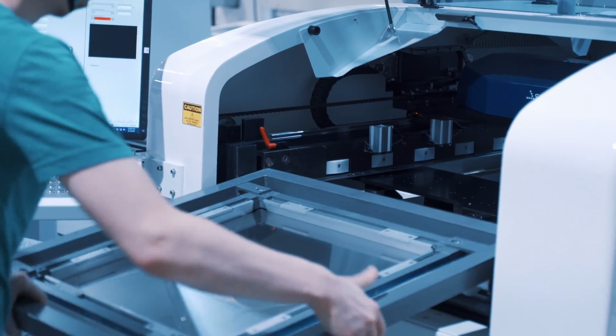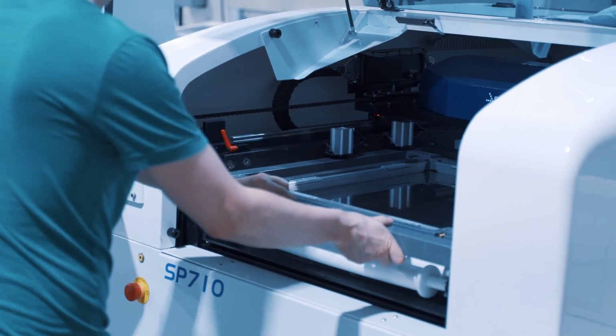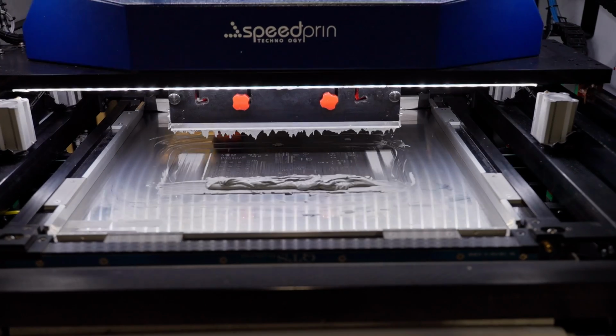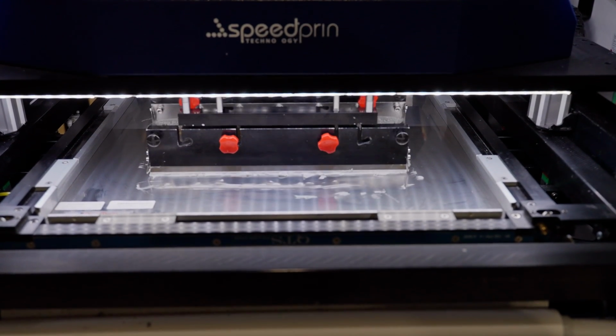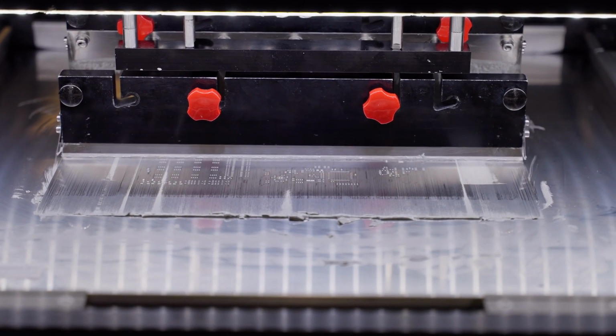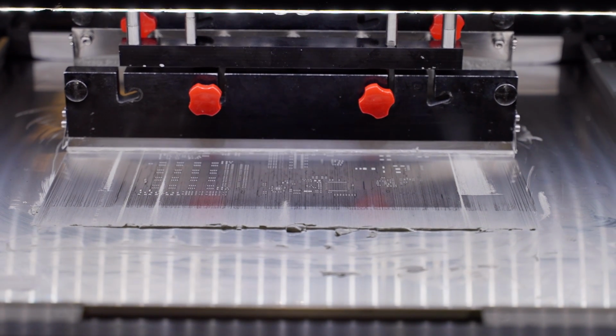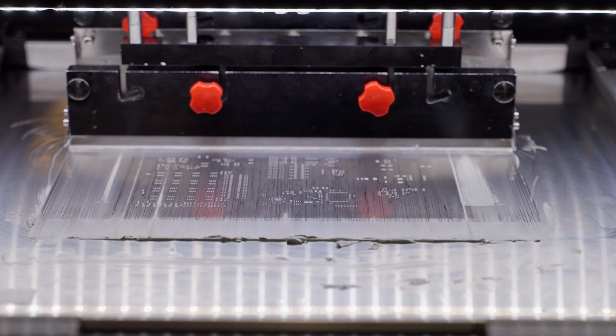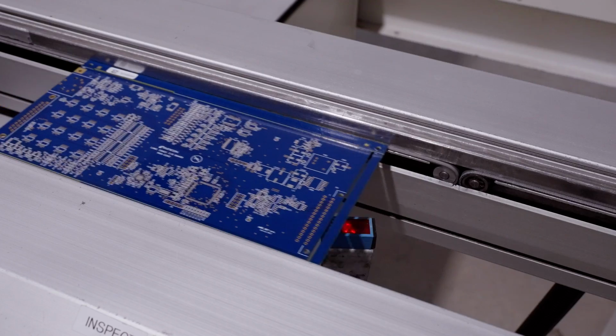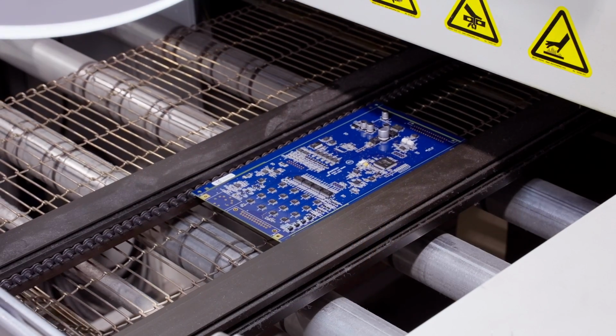Solder paste is a mixture of powdered metal and flux. We use a stencil and screen print the paste onto the boards. A camera aligns the PCB to the stencil, and a squeegee pushes the paste through the stencil's holes. After pick and place, the board goes through a reflow oven where the solder is melted.